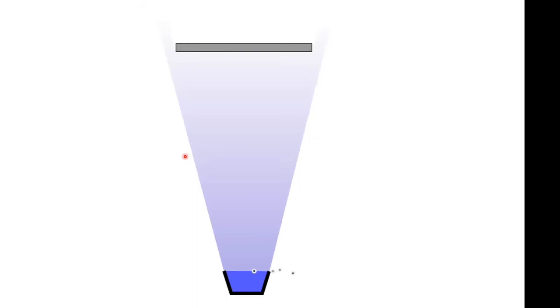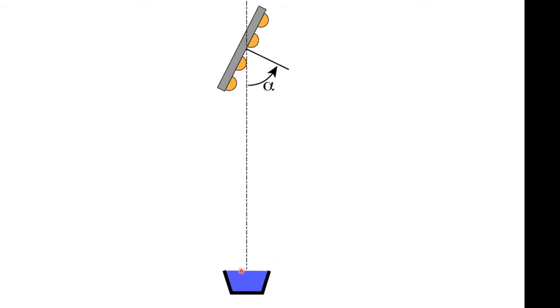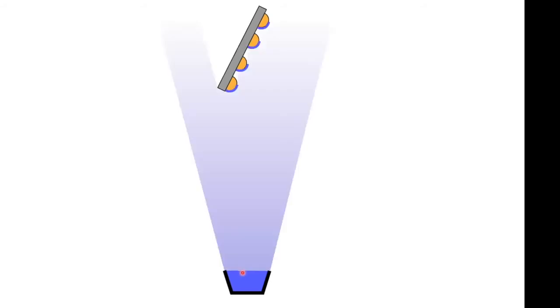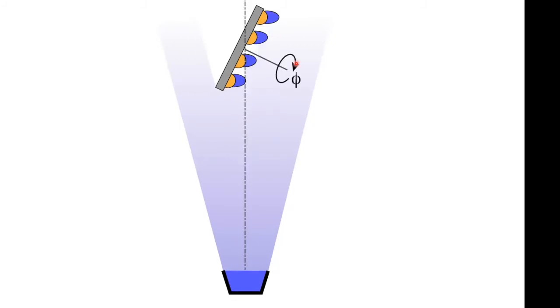How do we do it? We use a fabrication technique to make these tiny rods. We don't heat something and make a thin film, but it's related to this technique. We also have material that we like to use. We can also heat it in a vacuum chamber, but we use our substrate at this bizarre angle here with some nanoparticles, which means we can then get discrete growth because they're shadowing. Material will land here. What misses the first one lands on the second one, etc., etc. So in parallel, we can grow many structures. We can manipulate this, and then we can form interesting shapes.